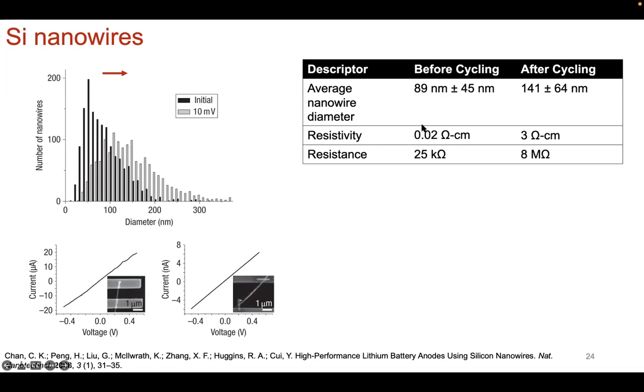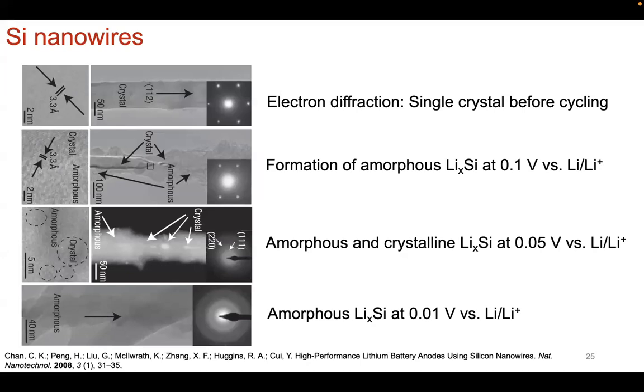And what we can see is before cycling, the diameter is 89 nanometers plus or minus 45. So this dispersion in terms of how controlled these nanowire sizes are is pretty large. But after cycling, the nanowire diameter increases quite a bit. So either there are lithiated phases that are trapped in there or what have you, but certainly there is some transformation that is not reversible, and thus contributes to the capacity fade that you see. Okay, but still a fantastic demonstration of nanowire growth and also usage in improving the electrochemical performance of silicon at the nanoscale. Now, since this work, there have also been quite a bit of studies done to really try to understand how lithiation occurs within these nanostructures.